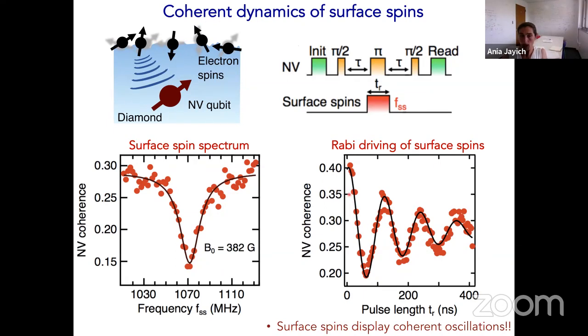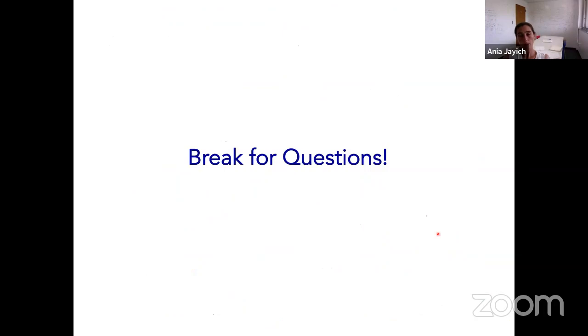So this is a plot showing, using the NV center as purely an optical readout here, that's dipolar coupled to these surface spins, we can drive these surface spins and measure Rabi oscillations of these surface spins using what's called double electron-electron resonance techniques. I won't get into the details of how we do this, but again, the main point is we can address these otherwise dark surface spins, which are hard to detect on their own, but using the NV center, we can address them. They're relatively coherent. We can drive Rabi oscillations in them.